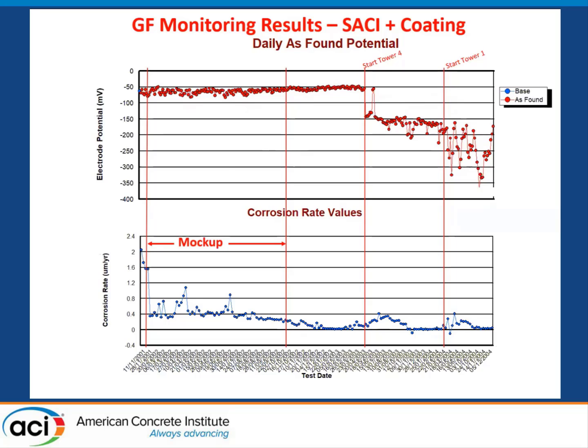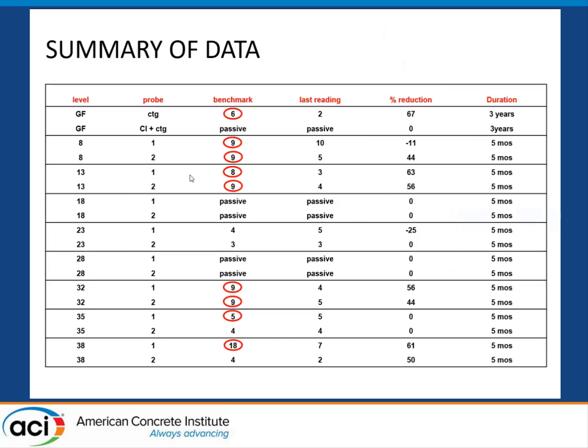And I think really for the owner, the engineer, this was confirmation that they made a good decision. You could see where it was just the coating. It seems that it was really struggling to try to mitigate that corrosion activity. And they went ahead and they installed these probes, not just in the mock-ups, but on floors 8, 13. So basically every 5th floor in one run in one of the buildings. And that was really a design decision of how much monitoring are we going to do to give us an indicator of how we think the repairs are performing. But what is interesting here is that the benchmark readings, over 50% of them were moderate to high corrosion activity. And within 5 months of completing the job, they have confirmation of data that shows good reduction in the corrosion activity. So really, it was a good indicator from the start that this was a successful approach.